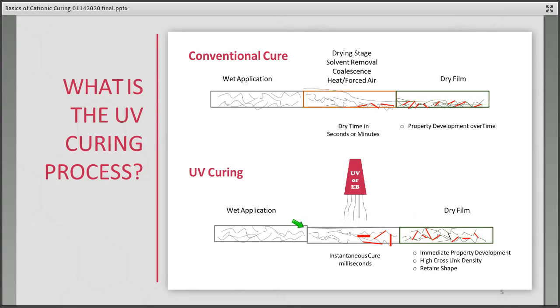Now for cationic curing, it works the same way as free radical cure. However, instead of instantaneous cure, and I'll be talking about this shortly, you may have cure stretching out over minutes or hours. You get your initial properties, which will help you do what you need to do, but you'll see an improvement in properties over time, known as dark cure.